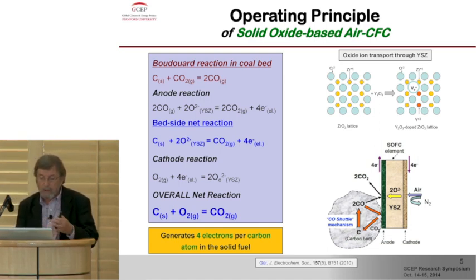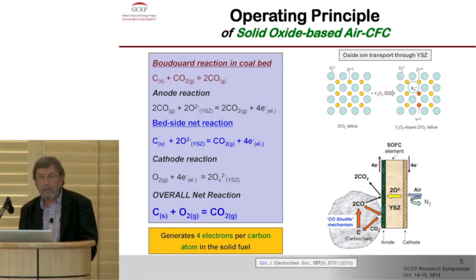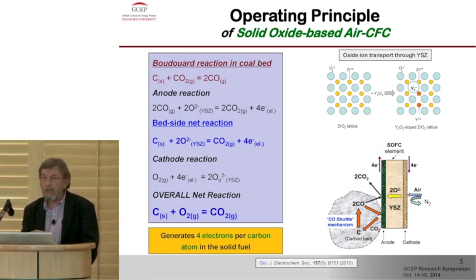So oxygen transports through the ceramic material only in the form of an ion, right? Not in the form of an atom or a molecule. Then this CO2 can react with a nearby carbon in the bed, forming more CO that feeds into the anodic reaction. So this shuttle mechanism, if you like, is self-feeding and provides higher kinetics than would normally be the case.